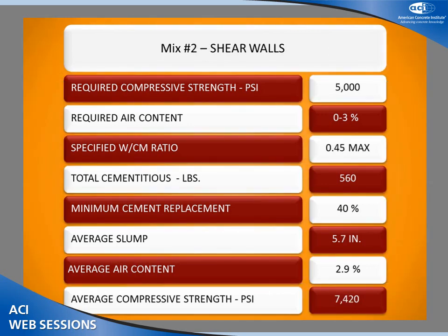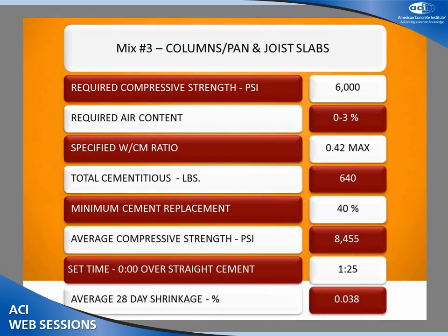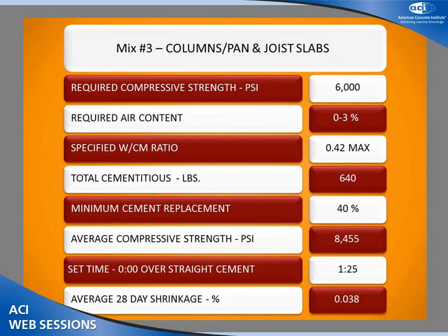Next one was the shear walls. We'll go through these quickly. 5,000 PSI. We're up at a 0.45 water cement ratio. Here we went up to a 560 total cementitious. Again, 40% replacement with the ash and slag. And very good performance strength-wise again. This was the flat work and the columns. 6,000 PSI. We were down to a 0.42 water cement ratio at 640 for total cementitious, and again 40% replacement. Compressive strengths were very good.